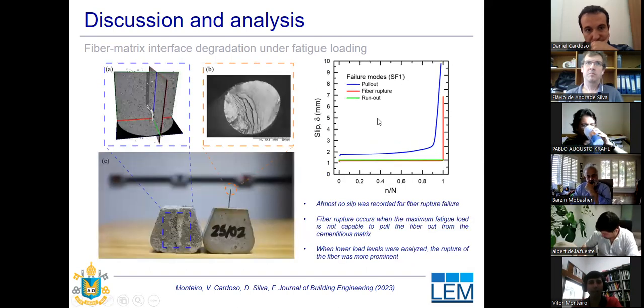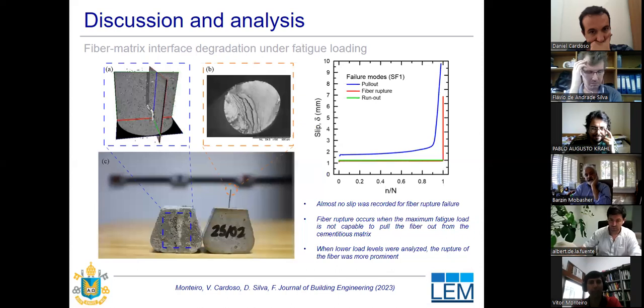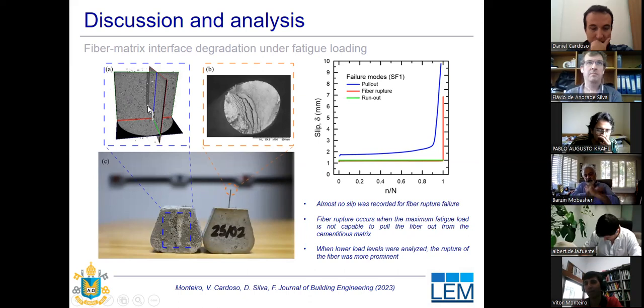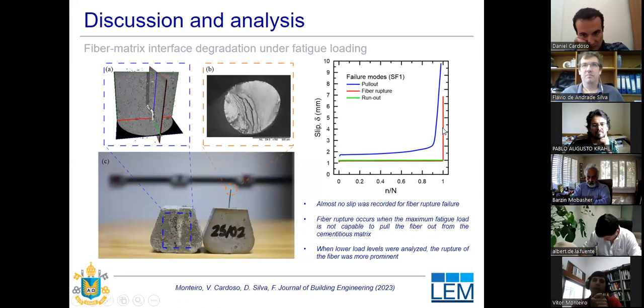For the next failure type, we could verify the degradation of the steel wire. That means that the steel ruptures inside the dog bone specimen. It's possible to verify through the CT scan image here that part of the hook is still inside the dog bone specimen after the fiber has been pulled, having fractured around the hook of the hooked end steel fiber. For this kind of failure, it's not possible to verify any significant slip evolution along the test. We can see here at the red curve that there is almost no slip until the fiber reaches the fracture, and then the fiber is pulled from the matrix.